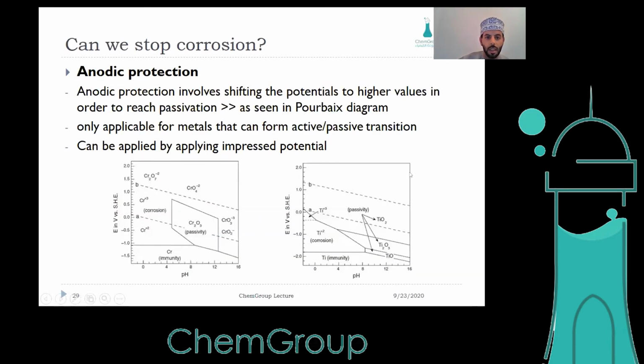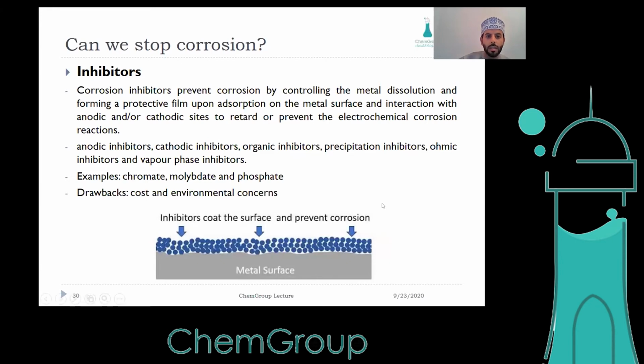The other one is inhibitors. Inhibitors are chemicals that prevent corrosion by controlling the metal dissolution and forming protective films that protect the steel or any other metal surface. There are many inhibitors, like anodic inhibitors, cathodic inhibitors, organic inhibitors, precipitation inhibitors, ohmic inhibitors, and vapor phase inhibitors. But the most used and most famous inhibitor was chromate, which is now not used due to its toxicity, and molybdate and phosphate. Chromate was the very best chemical inhibitor ever produced. But unfortunately, due to the toxicity of chromium-6, it's now banned and cannot be produced. So research now tries to form molybdate and phosphate, but the drawbacks are the cost and environmental concerns of these corrosion inhibitors.